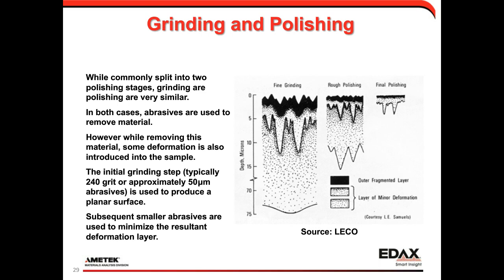use it to get a planar surface, and then step to smaller abrasives, which will then remove some of that initially introduced deformation and shrink the size of the deformation layer. So this schematic here, this is from a LECO handbook, kind of shows schematically as we go from fine grinding to rough polishing to final polishing, the idea that the outer layer becomes smaller and smaller, and the deformation layer becomes smaller and smaller. And so all we're trying to do is minimize the size of both of those at the end of our polishing procedure.